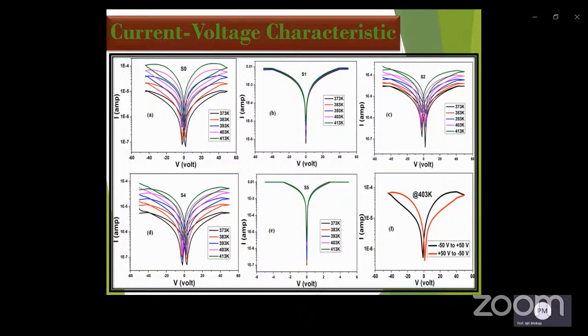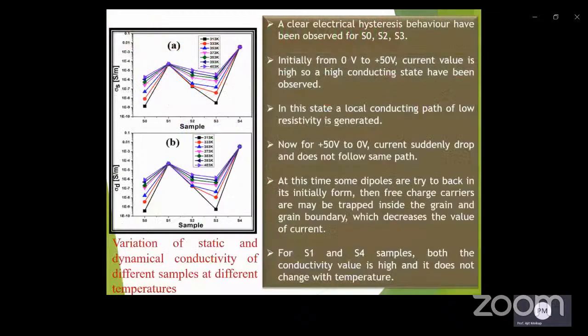Now, for decreasing voltage from 50 to 0, the current suddenly drops and does not follow the same path. At this time, some dipoles are trying to go back to their initial state, then free charge carriers may be trapped inside the grain and grain boundary, which decreases the value of the current.